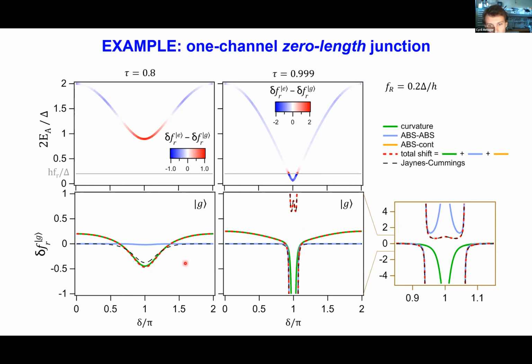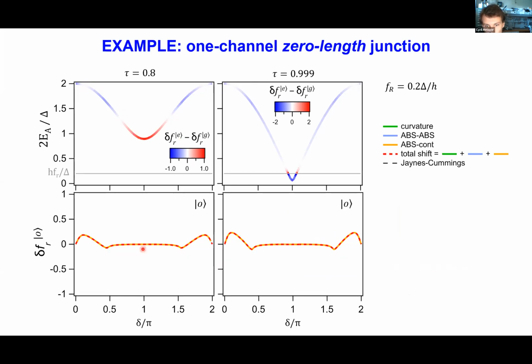Now, in the excited state, the shift is almost opposite to the one in the ground state, and so I plotted here the difference in excited and ground state, which is what we actually probe in two-tone spectroscopy. And in the odd state, the shift is almost 0, but it is remarkable that although this state does not disperse with flux and carries 0 supercurrent, it still contributes to a finite resonator shift, due to contribution from the continuum.